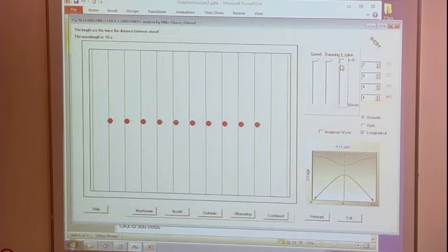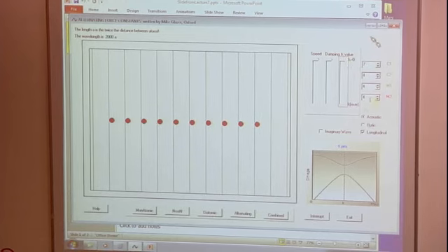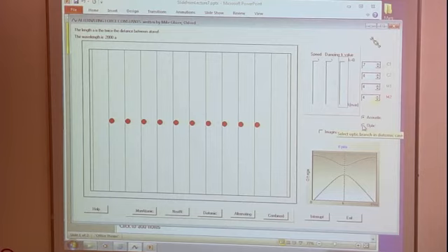So you can sort of view it as one big fluid. Everything sort of moves together. Now, if we go to k equals 0, it becomes 0 frequency. But we can click on optic here, and we'll get the optical mode. You see, the optical mode is each mass moving opposite the other mass in the unit cell. And you can see that this is something that should be high frequency because it's compressing the springs maximally.